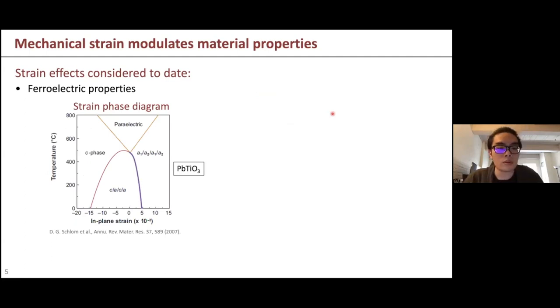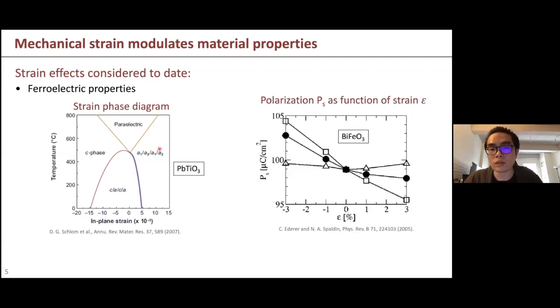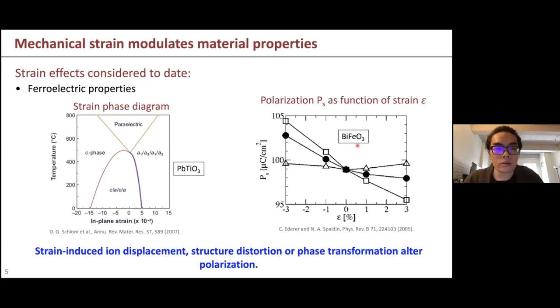So here I'm just showing a strain phase diagram where you don't really have to understand what these mean. These just mean different phases. But what I want to show here is when you apply an in-plane strain, because you change the symmetry, you can form different phases and then you can have different polarization strength. The second example is bismuth ferrite. Again, when you apply the biaxial strain, you can displace the ion or have some local octahedral distortion, so you can also change the polarization. So this is just an example of what the strain can do and what has been studied in the ferroelectric field, although I'm not going to go into detail today.